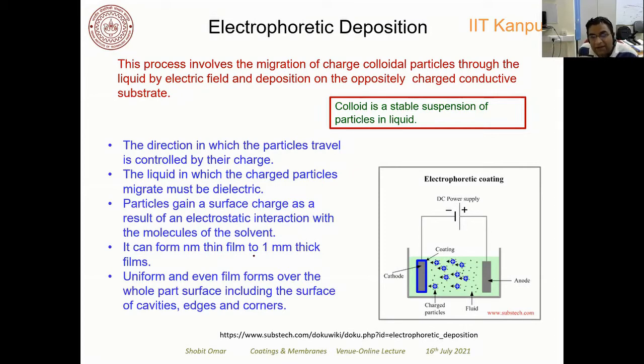It can form a nanometer thin film to a 1 millimeter thick film, right? So you can get a uniform and even film over the whole part surface. Even if you have a complex surface, you can deposit a uniform film, and that film can cover the cavities, edges, and corners, right? This is not possible in electrochemical deposition, because electrochemical deposition depends upon the current density. Normally on the flat surface you have high current density, and on the edges you have low current density. So normally the film thickness in electrochemical deposition is thin at the edges, while on the flat surface it is thick. So this is not possible in electrochemical deposition.